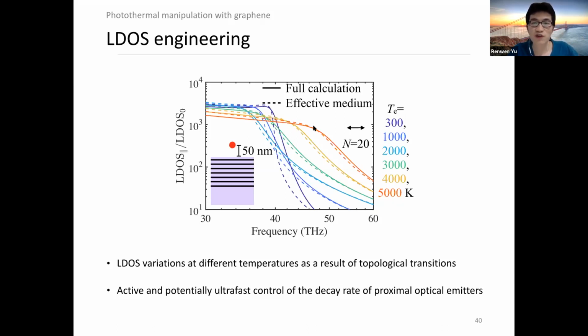And again, we can also see that the local density of states with large values extends to higher frequencies, as one can see before, because the epsilon-near-zero frequency is shifting to the higher frequency as we increase the temperature. So basically, we shift the hyperbolic shape also into the higher frequency. So it gives higher local density of states enhancement. So it can provide an active and potentially ultra-fast control of the decay rate of the nearby optical emitters.